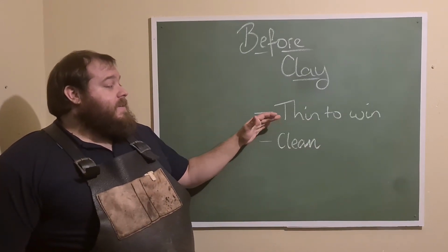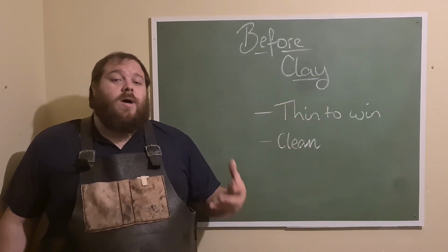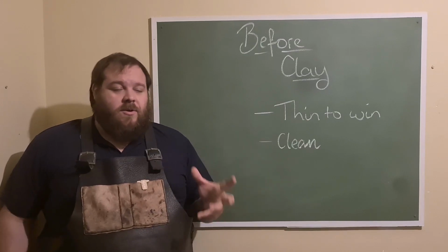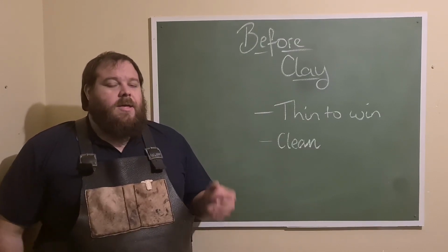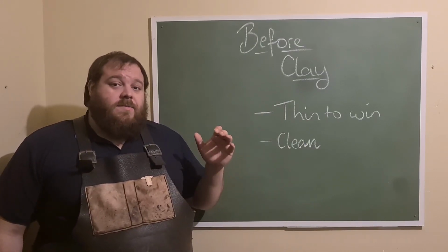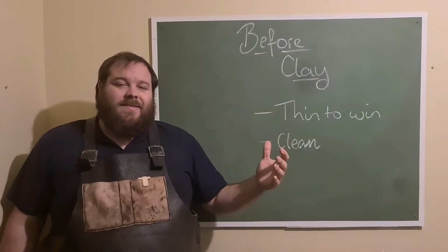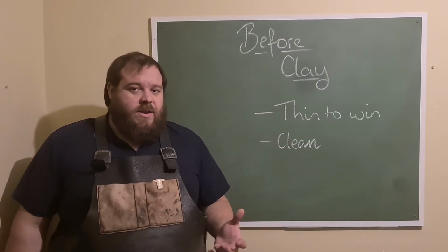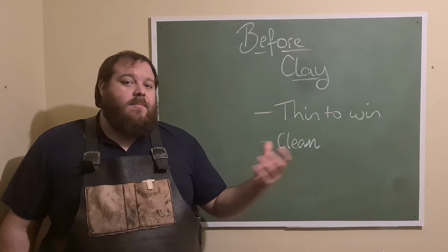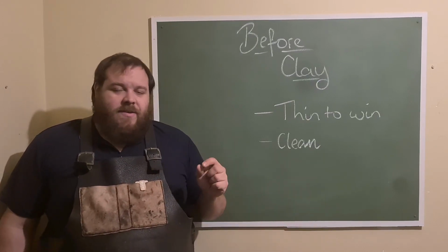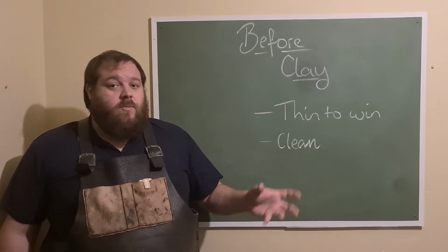So that being said, of course, the thinner you get, the more likely you are to get ripples in your edge or cracks. So it is a bit of a balancing game. My basic rule is to grind about 75% to finish before applying my clay, before doing my heat treat. It's a little riskier, but you get a much better reward in your Hamon.